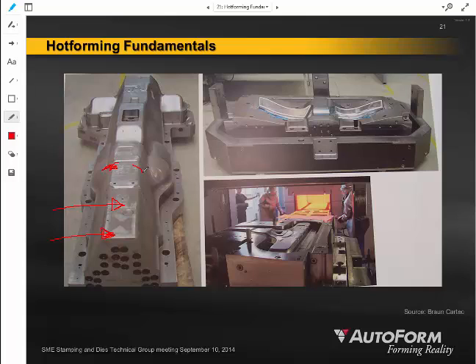That just doesn't make sense, that a material would have a predictable performance over such a wide range of temperatures. So we get abrasive wear of these tools caused by this aluminum silica coating, and then we also get adhesive wear or galling, where the coating will start adhering itself to the die. So we do end up having much higher mechanical maintenance of these dies. We've got to polish them, we've got to clean them more often. That also is a challenge.